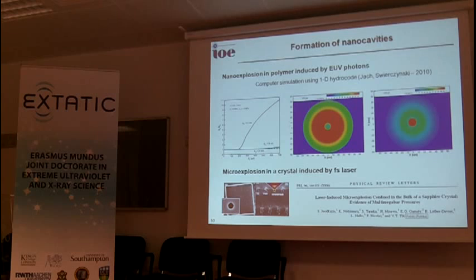However, we discussed it with some people working in this area, so it is more or less questionable. However, I think that it can start the ablation process, because a single photon can break a single chain of polymer. Okay? But to produce a void, such a nano bubble, we have to have more energy. And if we have one energetic photon, it will not be absorbed in this specific area. So we have to have a few of them.